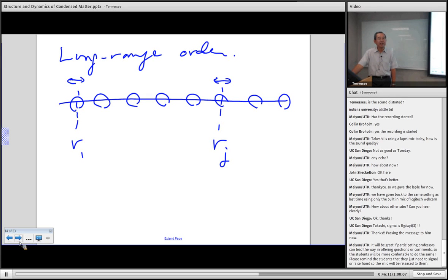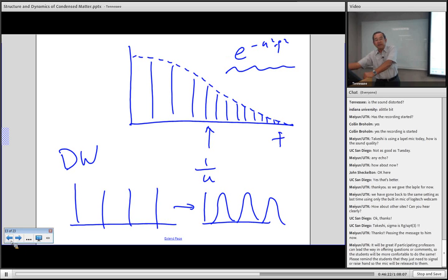Okay. So again, elastic scattering does not see each phonon, but simply sees the time averaged atomic positions. So you do not reduce the long range order, simply the intensity becomes reduced, because if the wavelength is small, that means Q is large, and 1 over Q corresponds to a real space length scale. At a small length scale, if the atom is not static, then you don't know where it is, right?